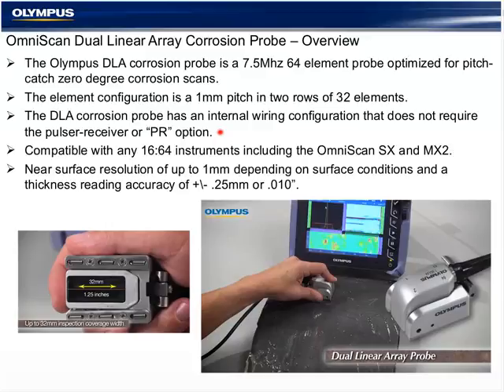Any of the 1664 instruments, including the SX, is compatible with the probe, and it is designed with a mechanical roof angle, frequency, and aperture configuration to provide approximately 1 millimeter near surface resolution and a thickness accuracy typical of most phased array instruments without auto gain correction, for about approximately 0.25 millimeters or 10/1000ths of an inch.